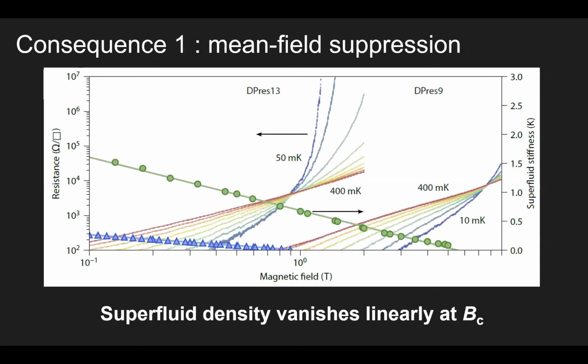You have seen there is a new regime of interaction-induced pinning of the vortex glass. And it has consequences for the superconductor-insulator transition and disordered materials. If I come back to this giant magnetoresistance peak, and I plot back-to-back superfluid density and resistance measurements, what you see here is two samples with two different BC, so different disorder. It diverges to megaohms, gigaohms, and the superfluid density vanishes exactly at this transition to insulation. And very importantly, you can see that it vanishes linearly, which is super important for what concerns quantum critical scaling of this quantum phase transition.